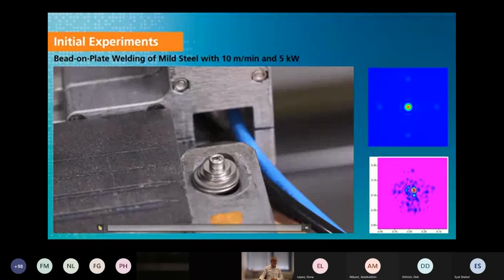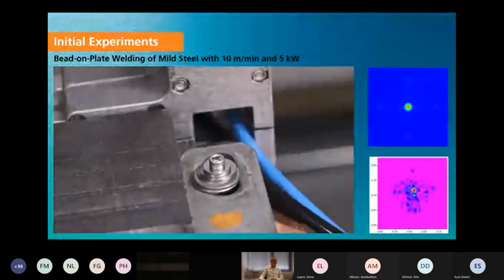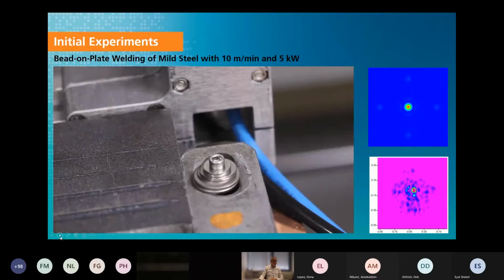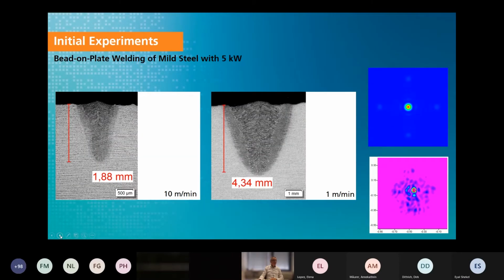So I will just run it again. In order to investigate what we have welded here, we have done two cross sections. On the left-hand side, you see a cross section of this bead on plate weld carried out with a speed of 10 meters per minute. We are reaching a penetration depth of almost 2 millimeters. On the right-hand side, you can see a cross section done with a welding speed of 1 meter per minute and 5 kW, and we can reach a penetration depth of more than 4 millimeters.